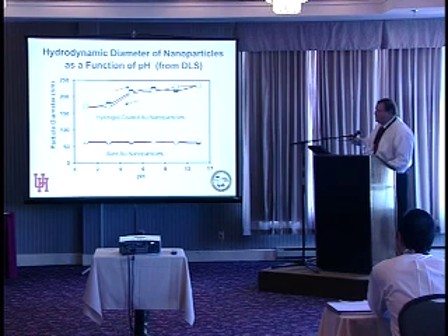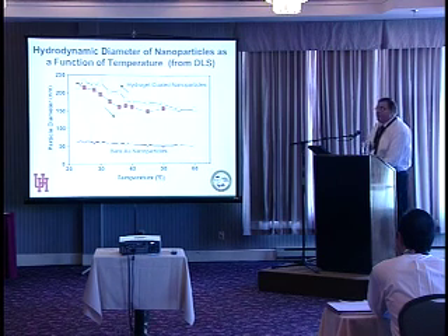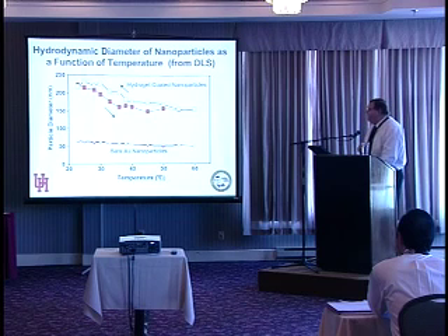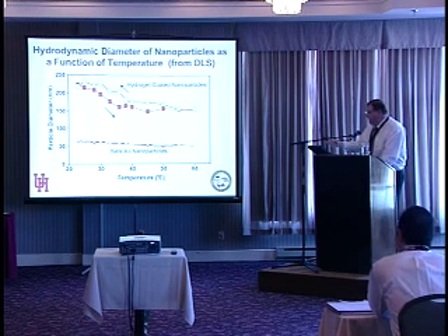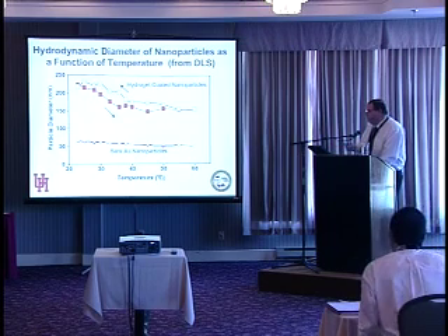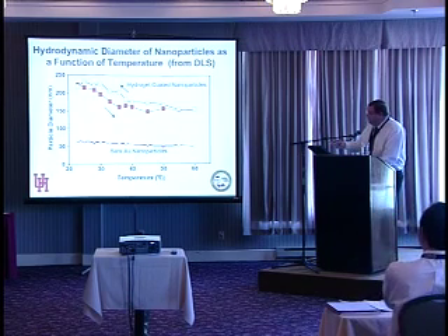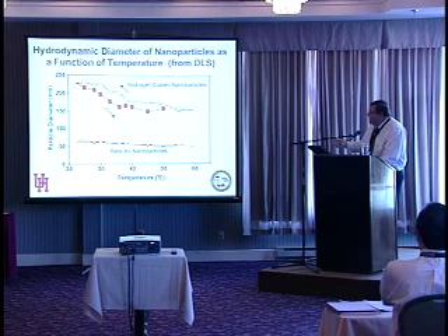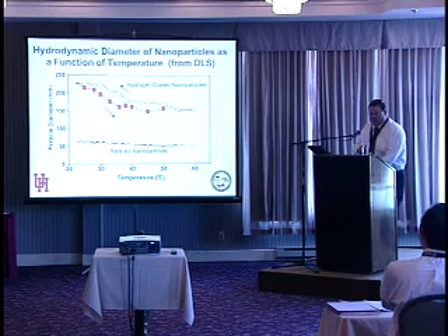This property is reversible for the hydrogel-coated nanoparticles. More importantly, the thermal collapse and reconstitution profiles illustrate similar behavior. Bare gold nanoparticles are essentially insensitive to changes in temperature. The hydrogel-coated particles, as we heat them up, the volume collapses, and as we cool them back down, they grow